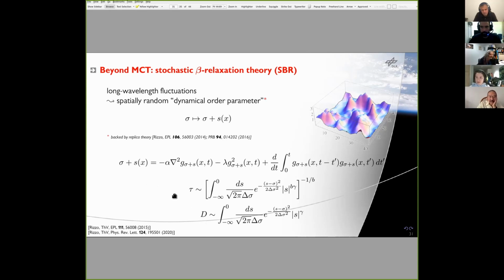Whereas, I mean, there's basically a distinction between the structural relaxation time and the mobility, where the mobility can be read off as the average mobility, whereas the relaxation time or the friction should be the inverse of the average. And the average of the inverse and the inverse of the average do not necessarily commute. And this is the reason why, as Tommaso, I think, also showed, the Stokes-Einstein relation is predicted to break down in the stochastic beta relaxation theory, because the product of D times tau no longer approaches a constant.